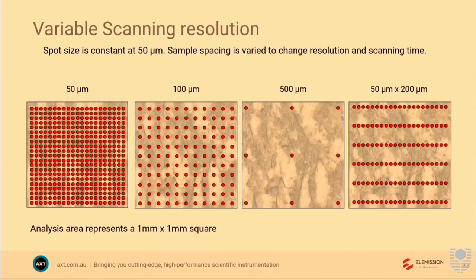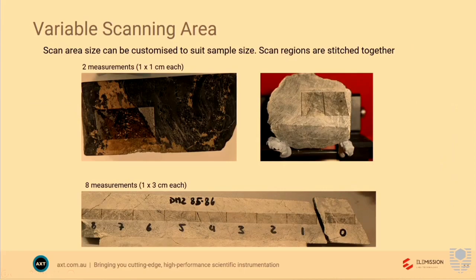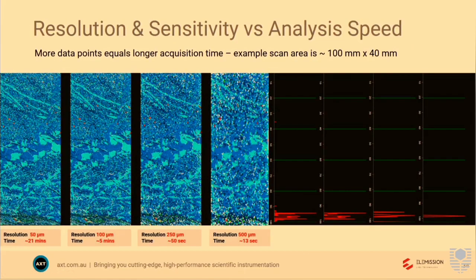So nominally it's a 50 micron spot size of the beam, so a totally different order of magnitude to SEM technology. Typically the lowest you'd go with SEM is about half a micron because of that activation volume underneath it, even though the beam's a lot smaller. So you compare half a micron to 50 microns, it's 100 times bigger. You can space out those beams, and by spacing them out you get a faster analysis. And you can also vary the scanning time. So ideally set up for core.